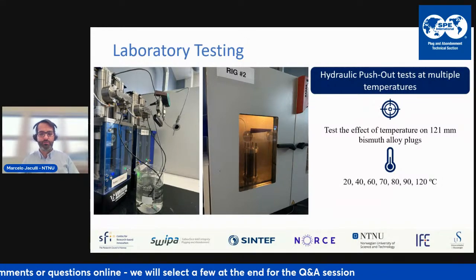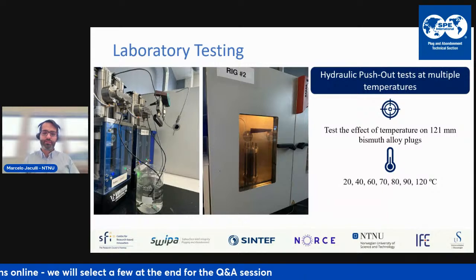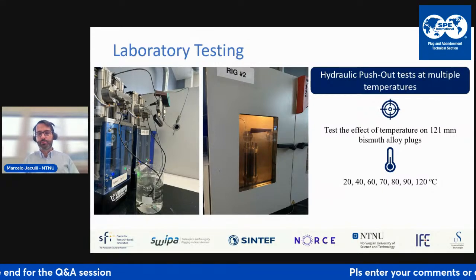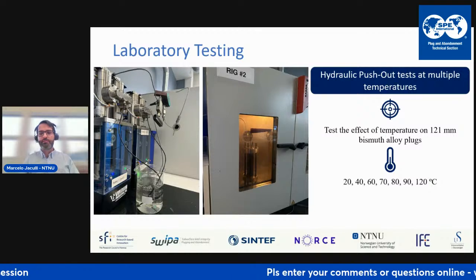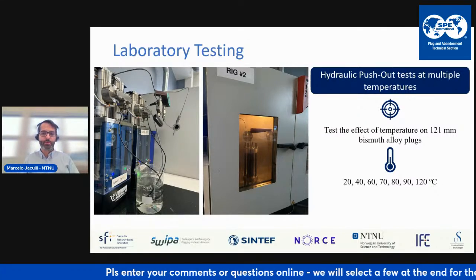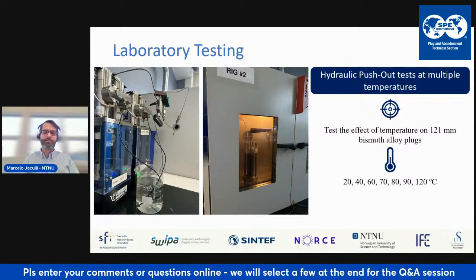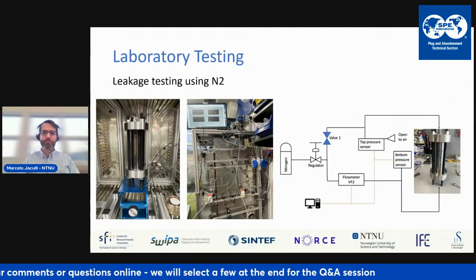We carried out that setup from the last slide and tested for several different temperatures. For this particular alloy, the eutectic bismuth tin, the melting point is 138. We tested very close to the melting point and also up to environmental temperature, to see what effect the temperatures would have on it.